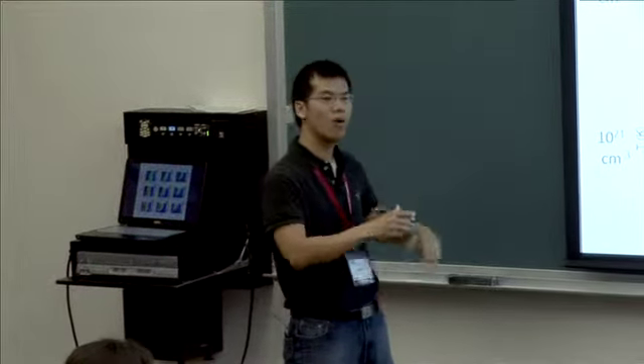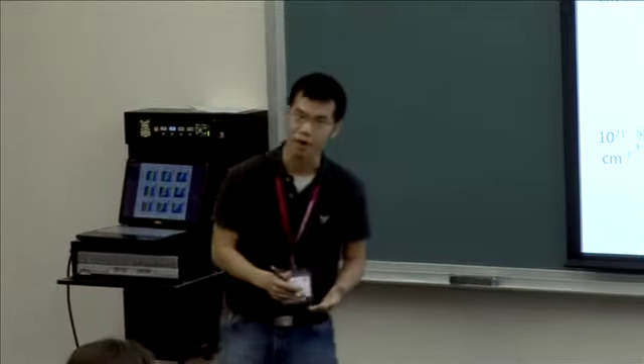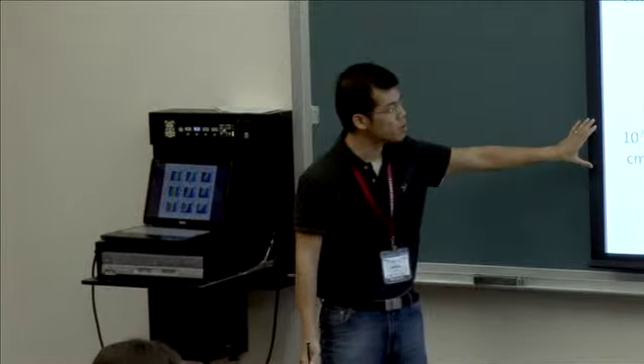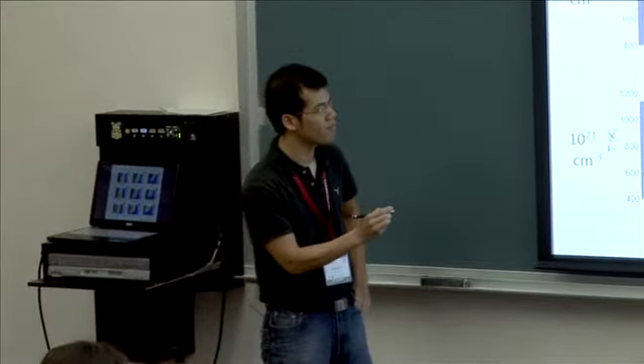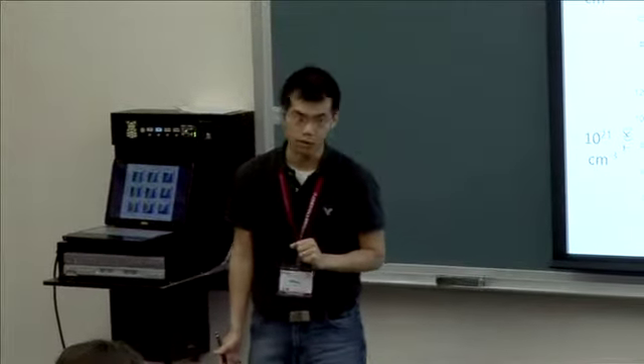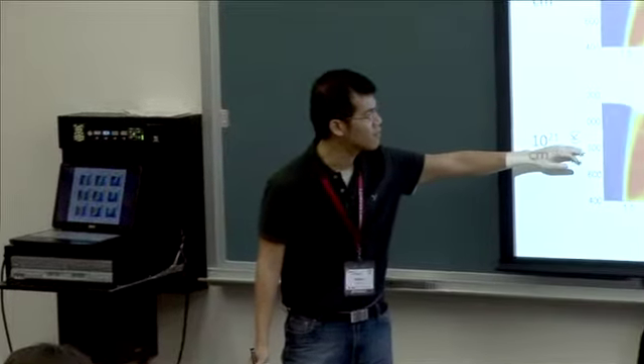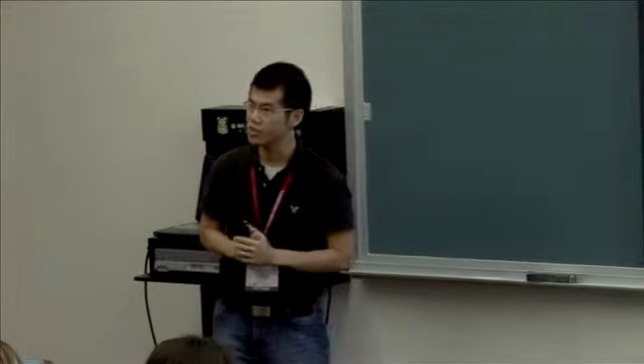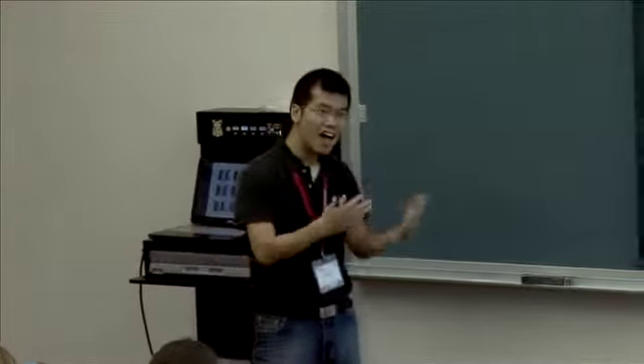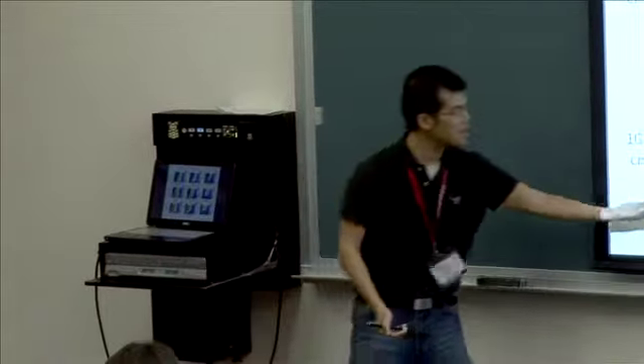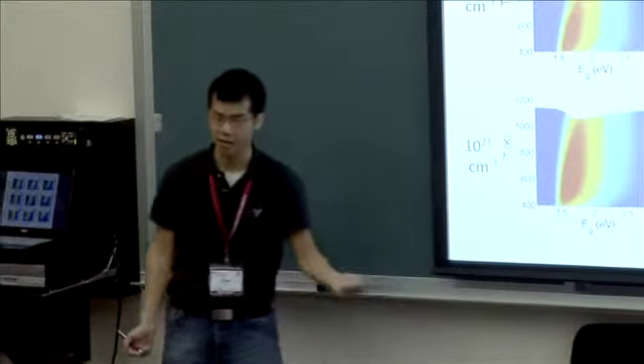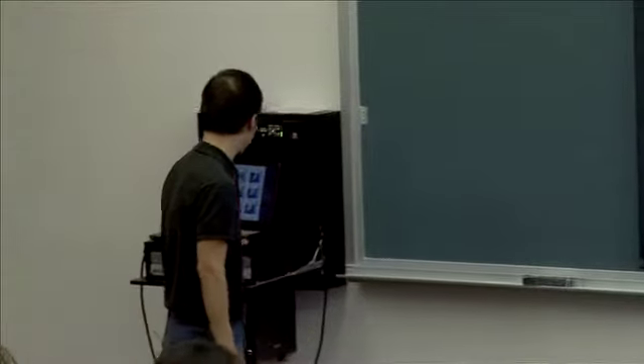It turns out that on the most optimal case, where you have a very small band offset, so a very small barrier between the two materials, and a fairly high doping level, it's possible to achieve a very high efficiency, about 30%, when you have a band gap of about 1.6 electron volts and when you operate at about 500 degrees Celsius. This is a very attractive temperature because it's not so hot, so we can still use an inexpensive material like stainless steel. But it's high enough so we can speed up the reaction. So you can see when we lower the temperature, the efficiency drops rapidly. So this is one aspect.